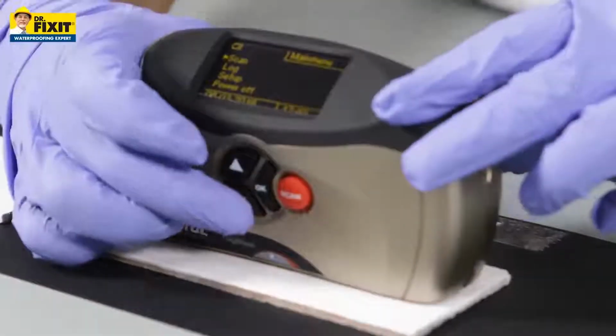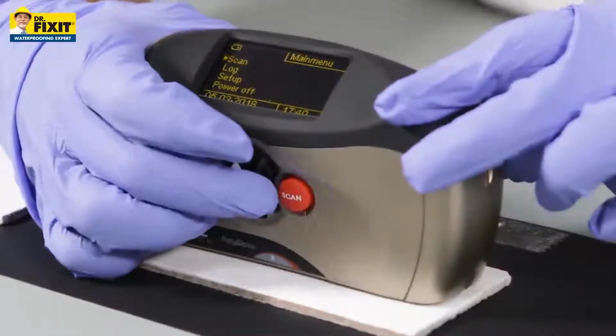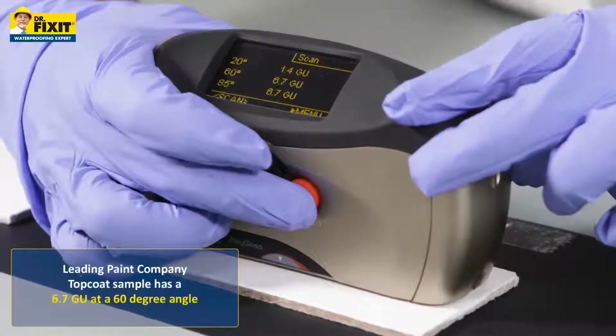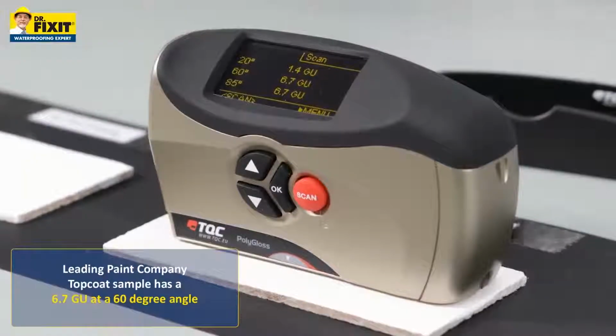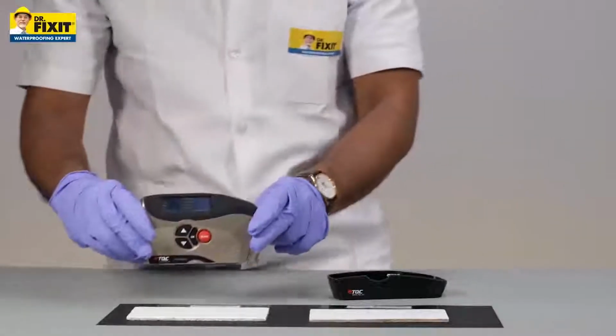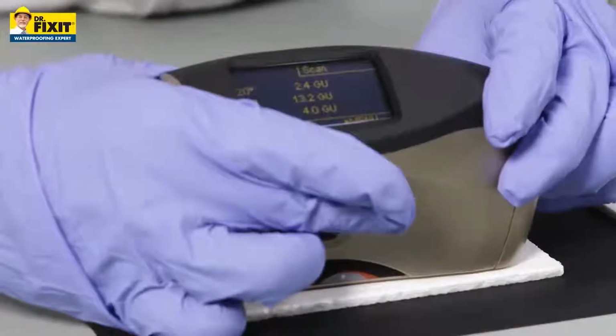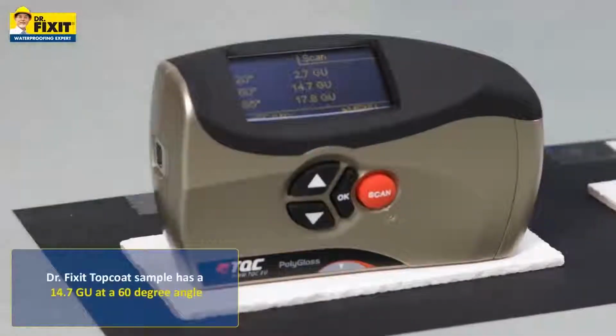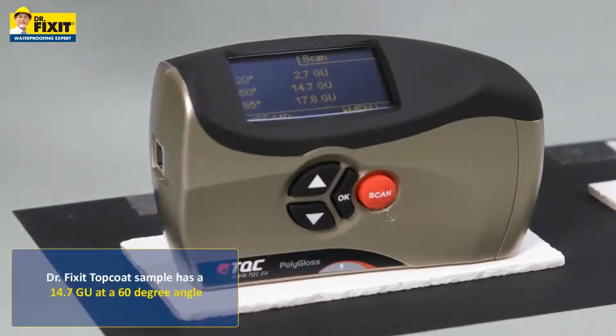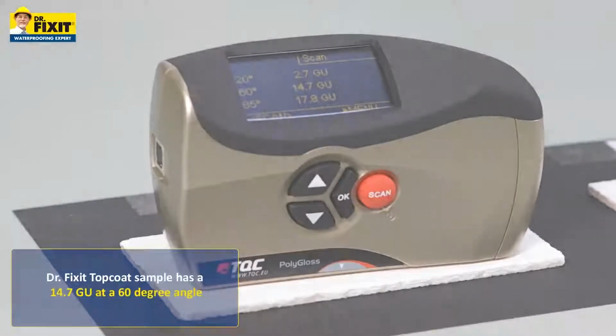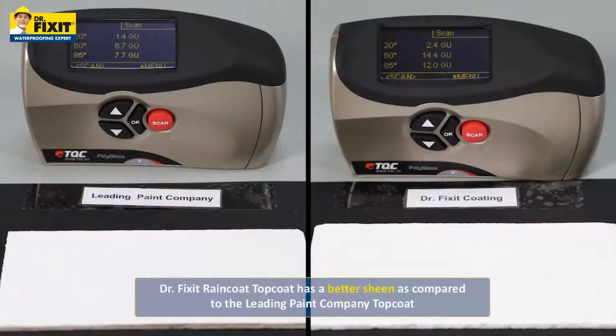We will place the gloss meter on the leading paint company's top coat sample. It has a reading of 6.7 GU at a 60-degree angle. Now we will place the gloss meter on the Dr. Fixit Raincoat top coat panel. It has a reading of 14.7 GU at a 60-degree angle. You can see from the results that the Dr. Fixit Raincoat top coat panel has a higher sheen as compared to the leading paint company's top coat panel.